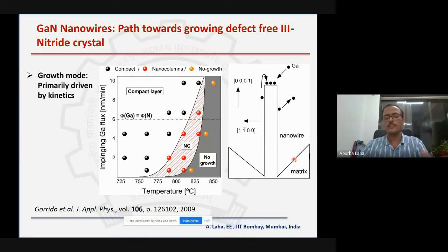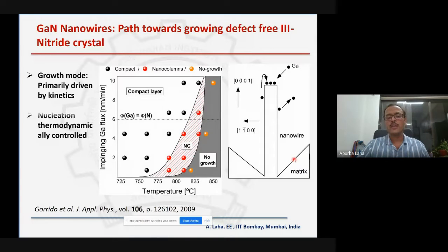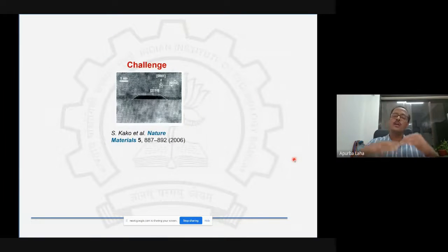So one way, as I said, we adopt our nanowire based technology, and I'm going to show you how we did. The challenge was, let's say this is a barrier, which is aluminum nitride, 6.2 electron volt, and in between you want to put gallium nitride, which is 3.4 electron volt, encapsulated by aluminum nitride. So it's essentially a quantum well structure.